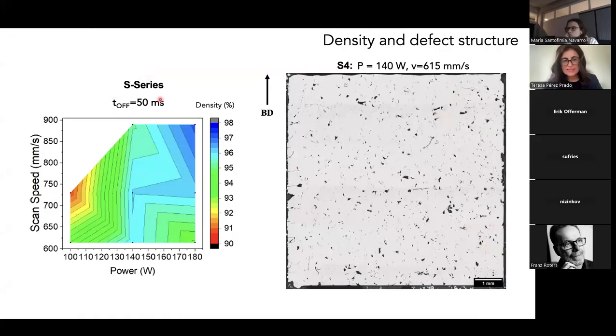This is what we call the S series. And we varied the power within this large region, 100 to 180, and the scan speed. You can see it here, and this is the density. The good news was starting to come, because now we see that over a relatively wide processability window, the density is already higher than 90, which was quite good for these materials. Here again, you have a cross-section optical micrograph, where we still have these fine cracks, I don't know if you can see it well, but the density was already much better.